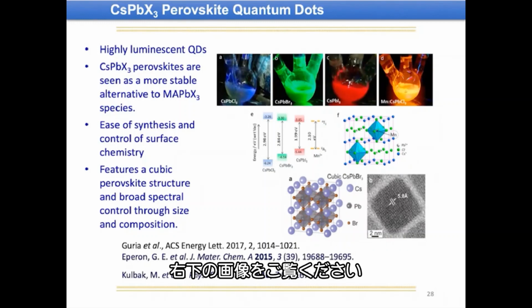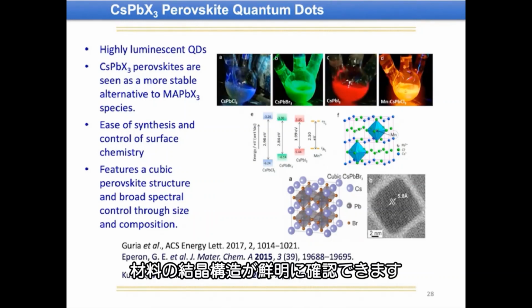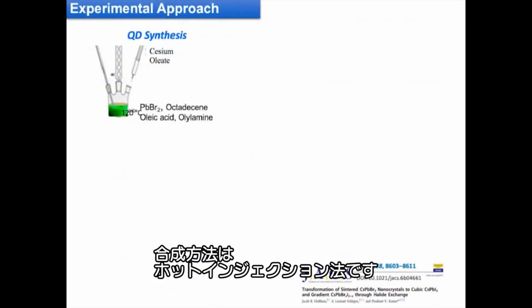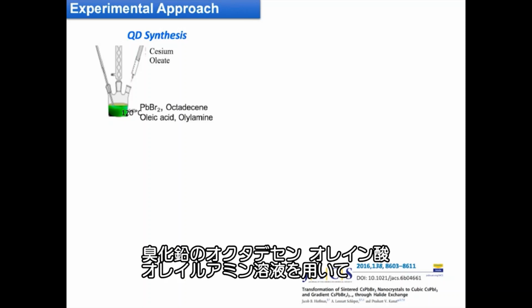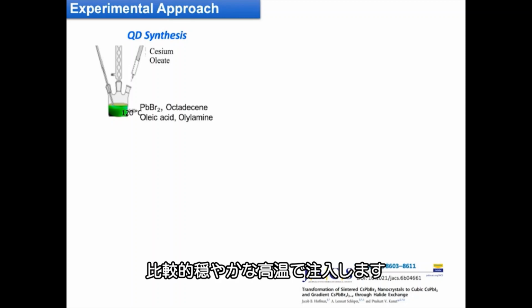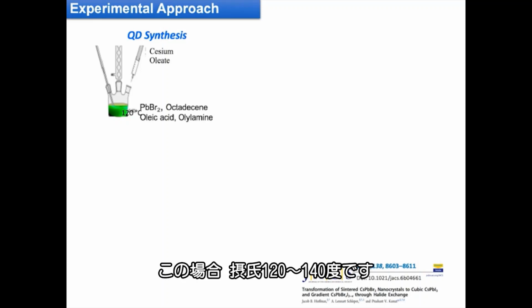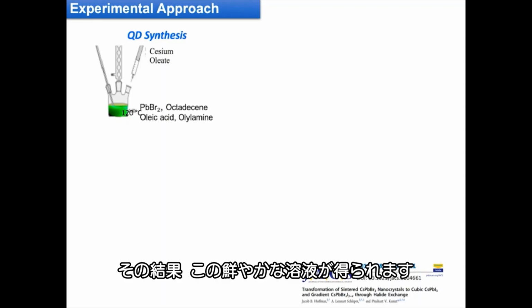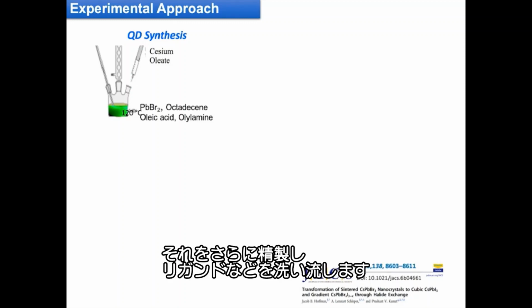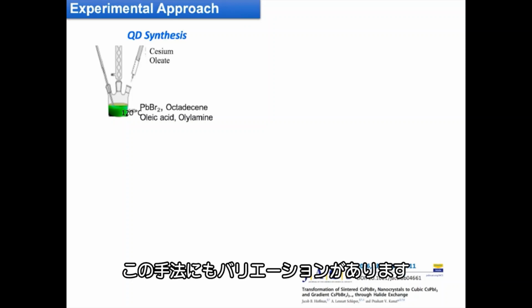You can see here on the bottom right a TEM image showing a very well-defined crystal structure of this material. How do you synthesize it? Again, it's a hot injection method. You use lead bromide in octadecene, oleic acid, and oleylamine, and then inject cesium oleate at a relatively mild temperature, in this case 120 to 140 degrees Celsius, and you get this brightly colored solution, which you can again purify, washing off the ligands and other things. Variations of this approach also exist.